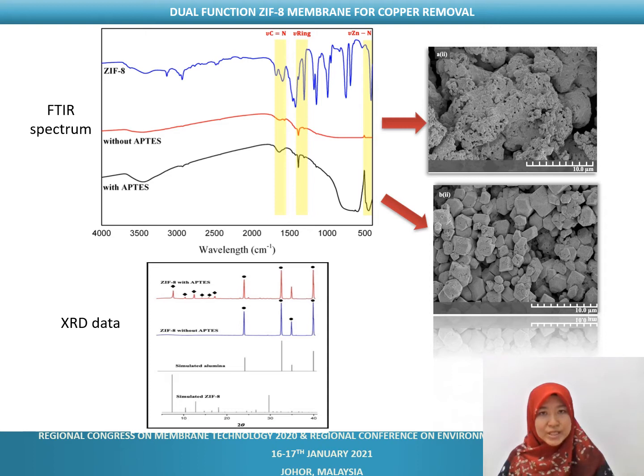For the first part, which is the effect of APTES modification, it is obvious from the FESEM images that the membrane grown on APTES modified alumina formed a crystalline ZIF-8 membrane with obvious hexagonal shape, the distinctive shape of ZIF-8. Whereas for ZIF-8 membrane prepared on unmodified alumina, the membrane formed an amorphous membrane with no distinct shape of ZIF-8 crystal. Therefore, it is proved that APTES enable better growth of ZIF-8 on the surface of alumina hollow fiber membrane because APTES can effectively enhance the heterogeneous nucleation of the ZIF-8 crystals, as mentioned by Wang et al.